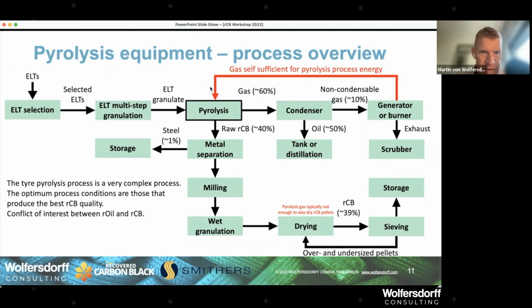Is there significant RCB loss during milling? No, because the fines is the output product. We want the fines, and everything coarser than the fines will stay in the mill until it is ground and leaves the classifier at the specified particle size to which the classifier is adjusted.